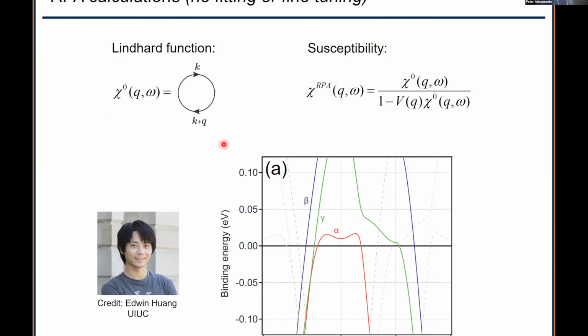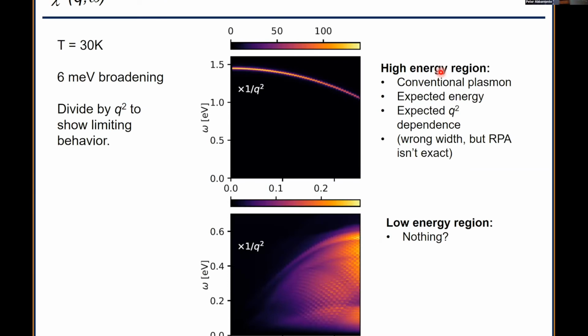And then he computed the Lindhard function, which is just a simple irreducible bubble. And then you can compute chi, the susceptibility that's actually measured in an experiment, in RPA. RPA means this chi 0 is the Lindhard chi, not the one with all the many body interactions in it. So if you do that, you see some things that make lots of sense. For one thing, you see a high energy plasmon, which we see in strontium ruthenate as well. In ours, we see it at 1.2 eV.